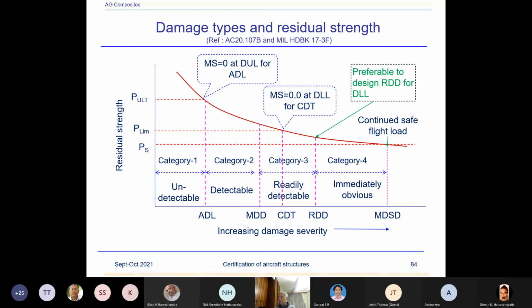Then in the factory, there could be some damages like BVIDs. In metal, of course, if there is a tool drop or a hailstone drop, some impact damage on the surface of a metal like aluminum, the damage will be visible. Unfortunately, in composite, you could cause damage by impact, but on the surface the damage may not be visible. That's typical of composite structure. However, that impact would have done enough damage to the internal plies in terms of disbond, delamination, fracture of fibers, and cracks. So the requirement covers BVIDs. I'll show in the next slide what the BVID, VID, and other categories are. But also certain small damages and holes, like a quarter-inch hole.